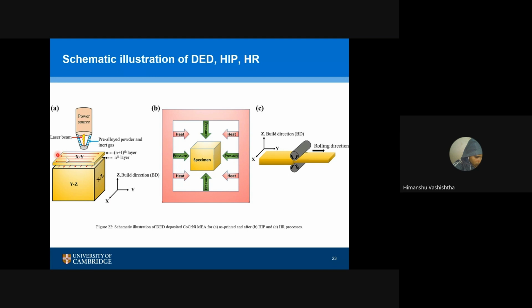So what we did, we printed using this raster scan strategy, in the XYZ directions. We believe XZ and YZ will give us the same microstructure and mechanical properties, while XY will give different properties because it's the top layer, which has not been heated multiple times, so it should have a pretty different microstructure. So we considered the XZ and XY surfaces. That's directed energy deposition, DED, not powder bed fusion or anything else.